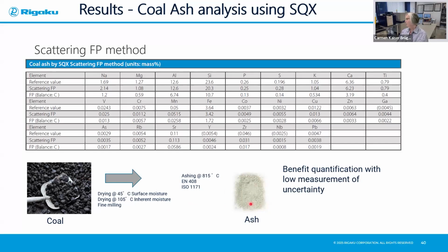So this ash needs to be prepared in a certain way. And of course, the ash content needs to also be part of the analysis. But the coal ash that I've given here also uses the scattering FP method. And as you can see, we can pick up elements from sodium up to lead. And as I said, it's important for us to measure the trace elements here as well.